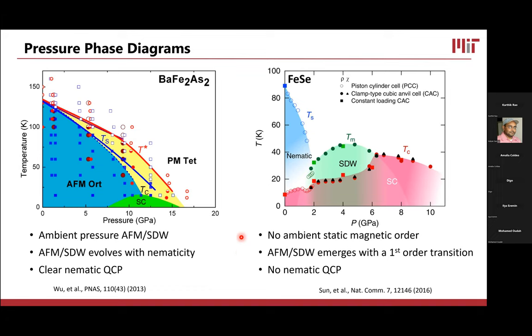Iron selenide has a very different picture. When we put iron selenide under pressure, we get a phase diagram that looks like this. The first thing that folks focused on in iron selenide is the fact that its nematic transition is not associated with a magnetic transition. If we look at the parent compound under zero pressure, as we cool down, we enter a nematic state at 90 Kelvin, roughly, and then somewhere around 8 or 9 Kelvin, we enter a superconducting state. And nowhere in this very large temperature range does it spontaneously magnetic order.